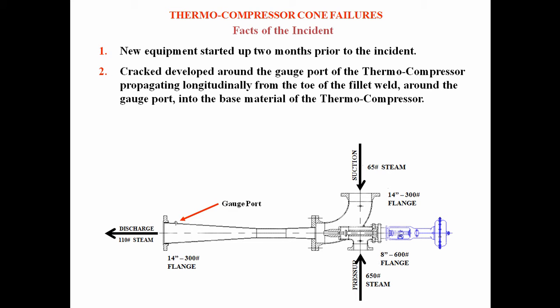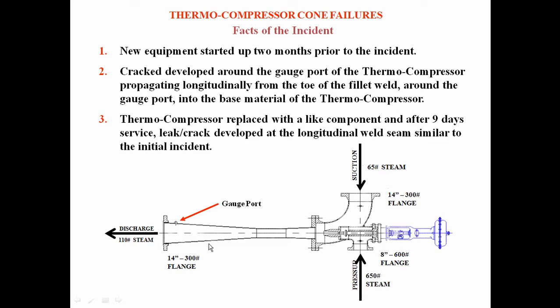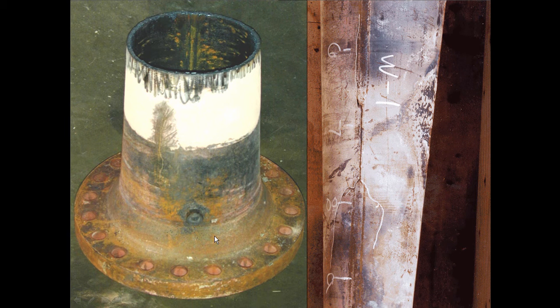So they change it out with a like component. This time they leaded this gauge port out in an attempt to fix the problem. But what happens now is after only 9 days, a crack develops in the seam weld of the thermocompressor cone, goes in this direction towards the large end to the toe of the seam weld, and propagates into the base material. Then it goes in this direction right down the center of the weld and makes this big Y pattern. And this is what the two failures look like.